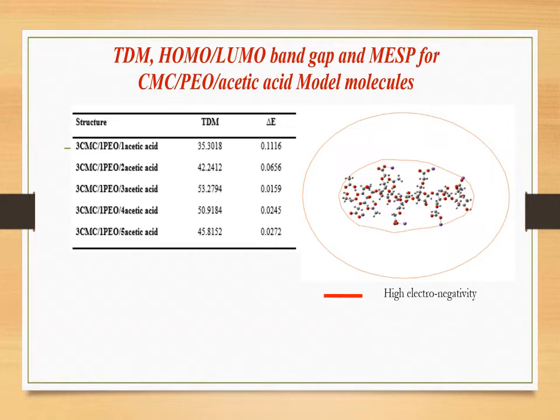The same behavior has been obtained theoretically using molecular modeling, where we see that the conductivity or the reactivity increases with increasing acetic acid content up to 3 units, then it starts to decrease at higher concentrations, which means that increasing acetic acid from 1 to 3 units increases the mobility, and hence the conductivity increases, and at higher concentrations a charge carrier agglomeration occurs, then the conductivity decreases.